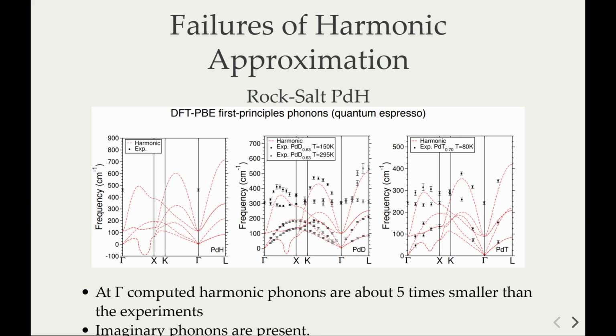And then if you look at the spectroscopy measurement we have of the phonon at gamma, the experimental point is that very small point here, while what is predicted by theory is 5 times lower. So there's an error of a factor of 5 from DFT calculations.